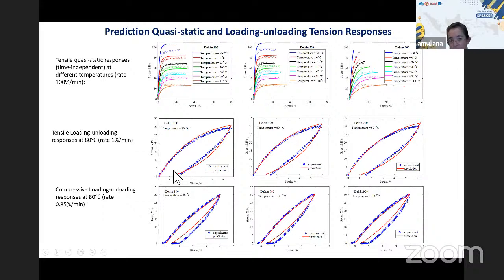As you notice here, we see a large area. This is the amount of energy being dissipated, right? While tension shows larger energy dissipation compared to the compression. This energy dissipation is partly due to microstructural changes and also due to the viscoelastic response. So as you see here, the response of the material changes with temperature. And in addition, it also shows the energy being dissipated, right?